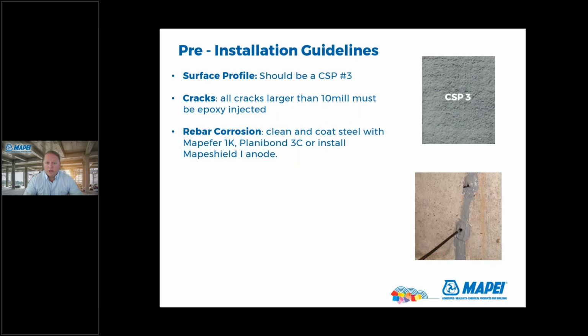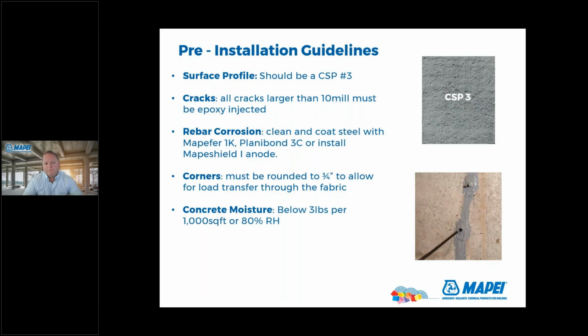If you have any corrosion on your rebar, you're going to want to clean that. You want to coat the steel with a coating. MAPEI has this Mapefer 1K. We have a Planibond 3C with cementitious or epoxy coatings. You can install anodes, basically add some energy back into the system from the energy, the electrons, that were lost due to corrosion. You're going to want to make sure the corners are rounded to 3/4 of an inch, and this helps allow for load transfer through the fabric.